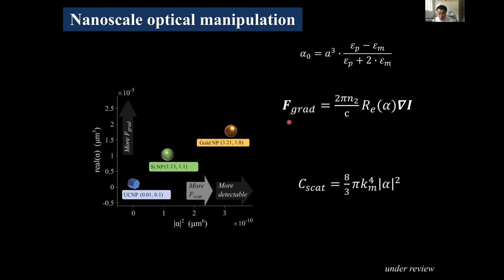For your gradient force, which is the trapping force, it is in relation to the real part, and your scattering is in relation to the amplitude. The scattering matters because you want to see some scattering to detect the trap stiffness. The challenge with nanoparticles is that gold particles have a higher value, but the trap stiffness is not that high. So you still need high power, and then you're heating your surrounding biological sample. And if the size gets really small, the scattering is also quite small.